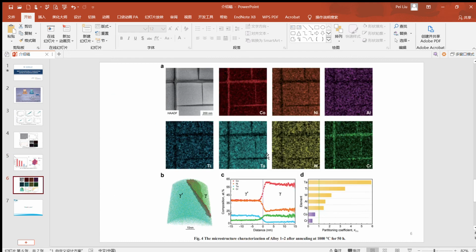In figure 4, the microstructure characterization of alloy 1-2 after annealing at 1000 degrees for 50 hours is shown. To further understand the element distribution in the gamma and gamma-prime phases of the experimental alloys, element mapping is performed with high-angle annular dark field scanning transmission electron microscopy, and nanoprobe and atomic-scale phase compositions were measured using APT. Compared to the partition coefficients in the reported studies, the partitioning trend and extent of each element is consistent even though its elements are contained in different cobalt-based alloys.